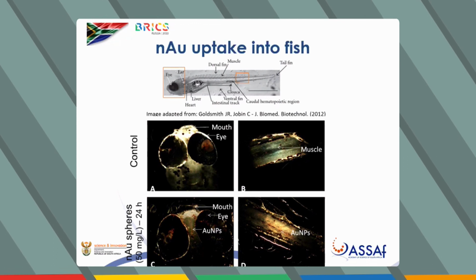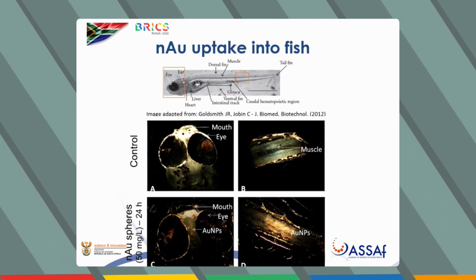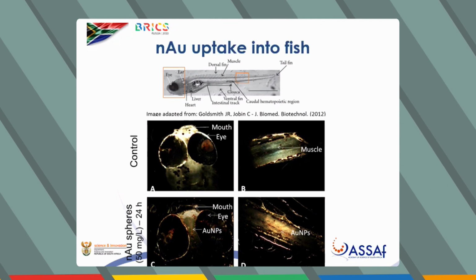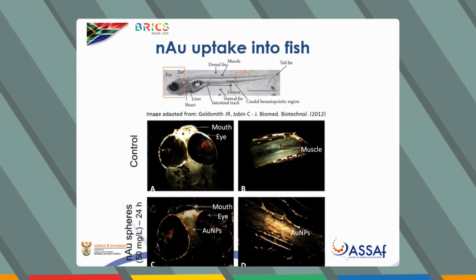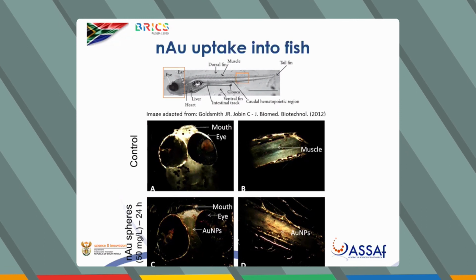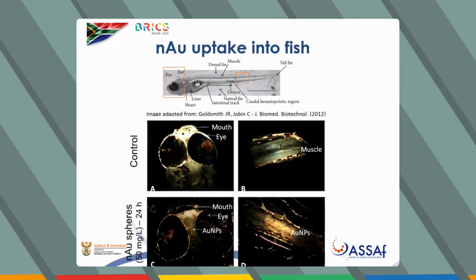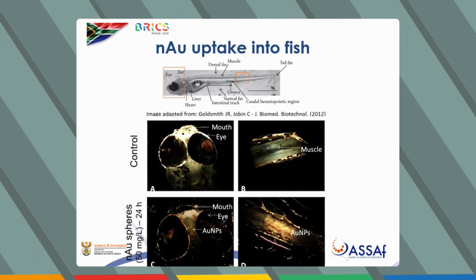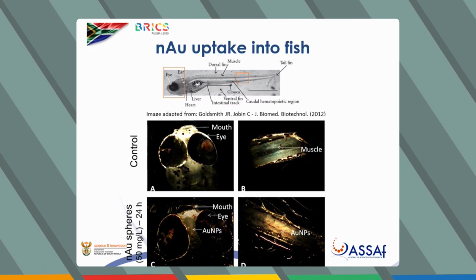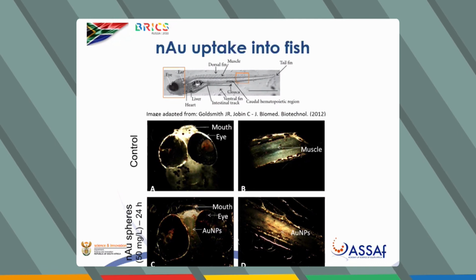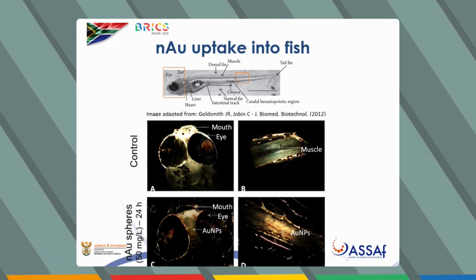And what we immediately noticed is that the fish is swimming, so it's obviously feeding and gulping water, and ingesting these particles. We've then also observed particles in the intestinal lining. And as we know, fish have bacteria within the intestinal lining. Since one of the applications of gold is as a bactericidal, we have already noticed that there is a shift within the bacterial community of the gut in the fish.